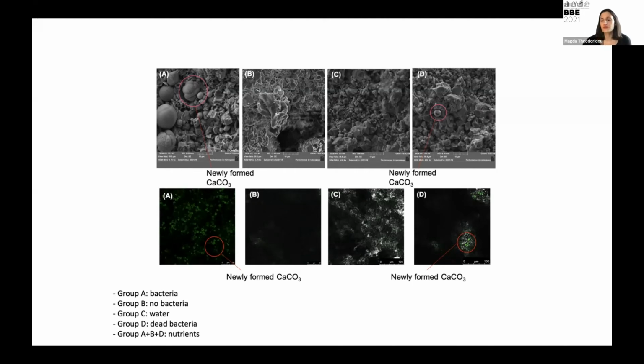And the second row of photos shows the microscopic aspects attained using confocal microscopy in specimens stained with a dye. And that dye has the ability to stain all the newly formed calcium carbonate particles. And the results agree well with the SEM. Basically, what you can see above has been repeated in a way in the second row of pictures.